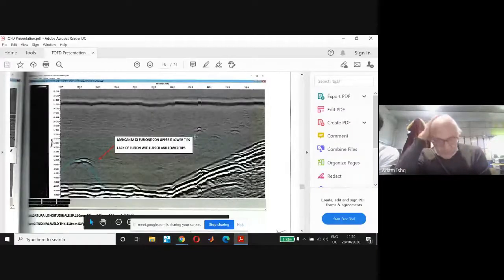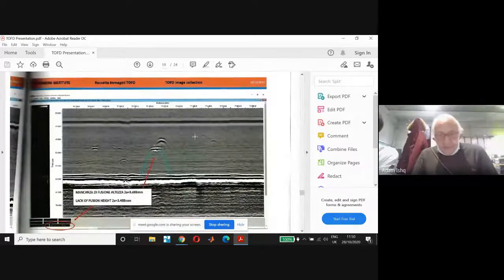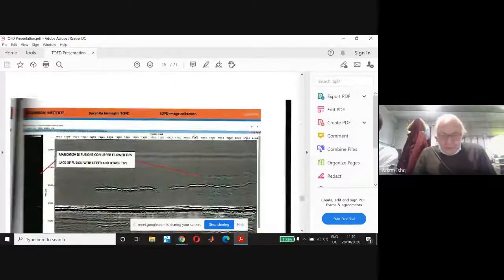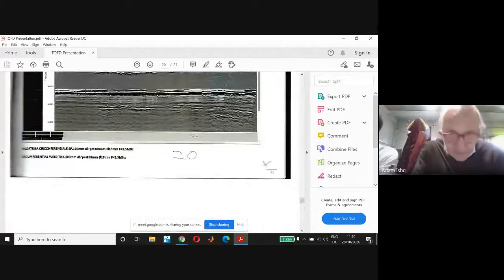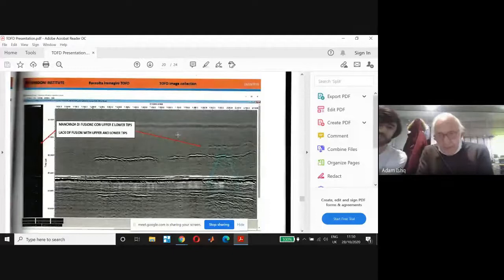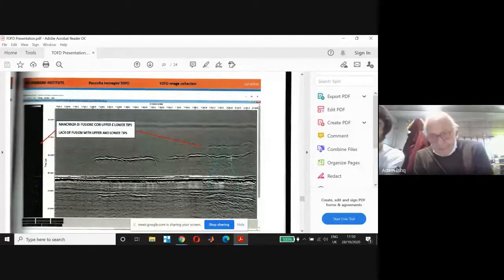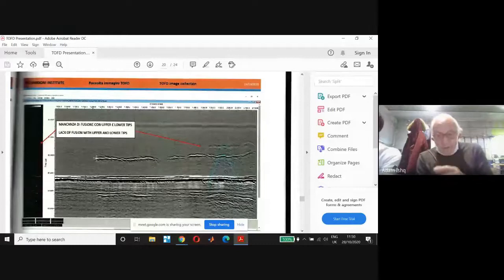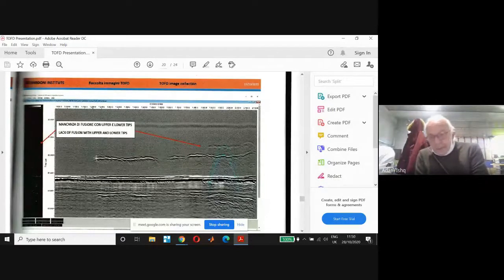In any case, the only limit of time of flight is the following: you need to place the probe on both sides. You see how well you can see, fantastic. This is a lack of fusion again. So we have a reference collection as for radiography. Time of flight is better than radiography because you have images forever.